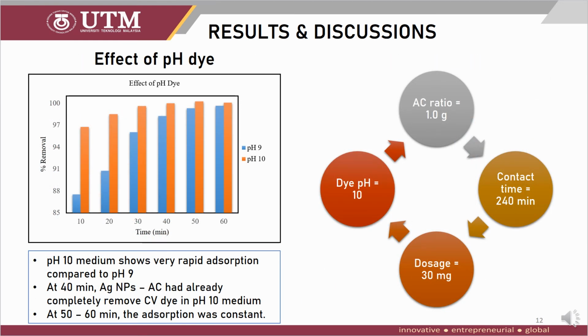Since pH 9 and pH 10 show better performance in removing crystal violet dye, further experiment needs to be carried out to know the potential of both of these pH. As you can see here in this figure, pH 10 medium shows very rapid adsorption compared to pH 9 starting at 10 minutes. And at 40 minutes, the AgNP-AC had already completely removed crystal violet dye in pH 10 medium. And at 50 to 60 minutes, the adsorption was constant throughout the experiment.